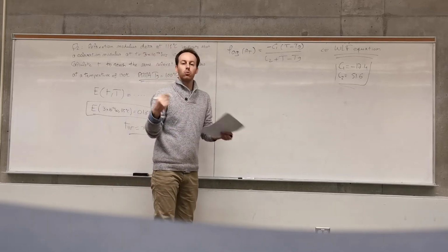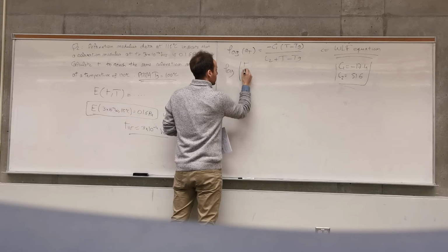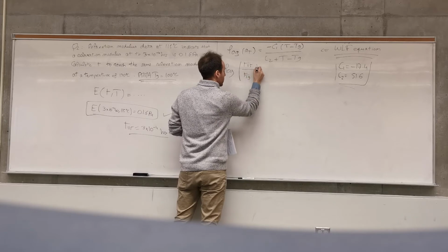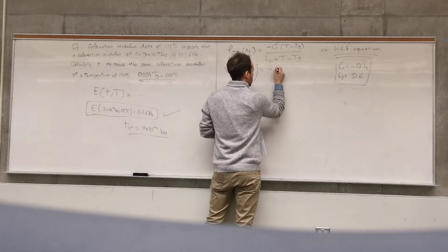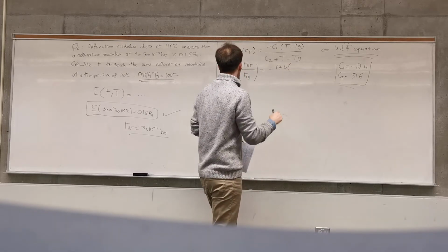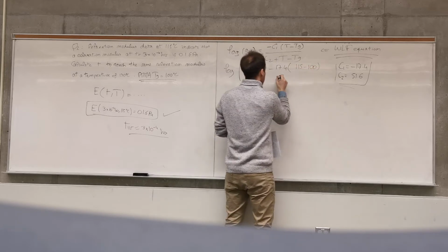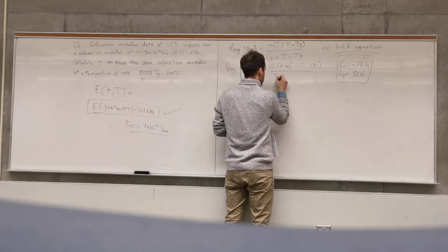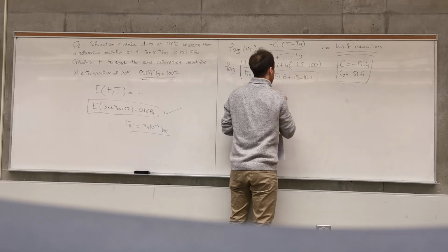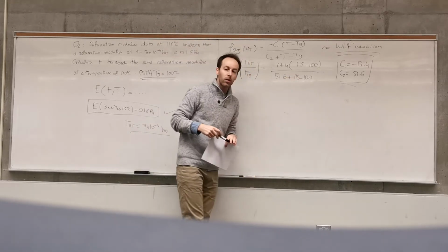Okay, so let's start as we just discussed. So we say log of time at 115 divided by time at Tg is equal to minus 17.4 times the temperatures. So we have divided by, okay. So just one thing here, the temperatures are supposed to be expressed in Kelvin, okay?